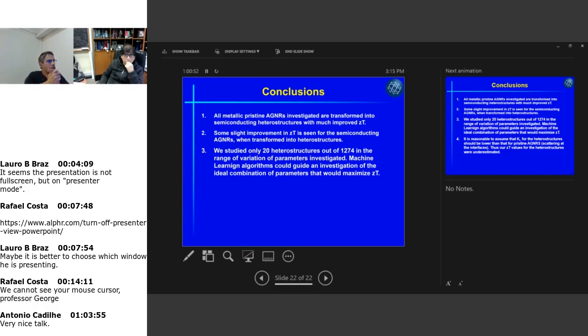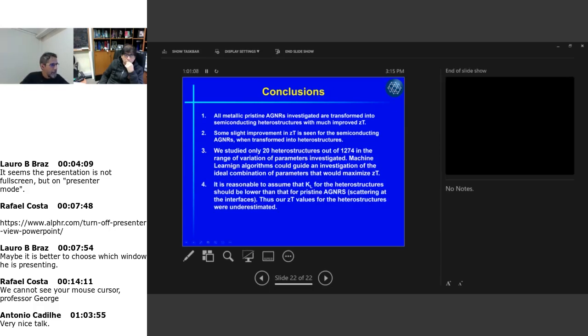So some machine learning algorithm could be used to try to see how you should change the parameters to maximize ZT. And as I said, we expect that kappa L is smaller for the heterostructures because of the scattering at the interfaces. Thus, our ZT values for the heterostructures were underestimated.